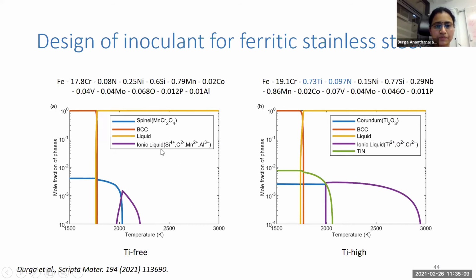And then we also found that it had picked up some oxygen. So when we look at the equilibrium phase fractions, we see that at high temperatures, we have the oxide-rich phases like spinel in the case of the titanium-free material. And in the titanium high case, we have corundum forming at high temperature, and also titanium nitride. From literature, we also know that this titanium nitride can nucleate on the corundum itself. So hopefully we thought that this would be favorable.